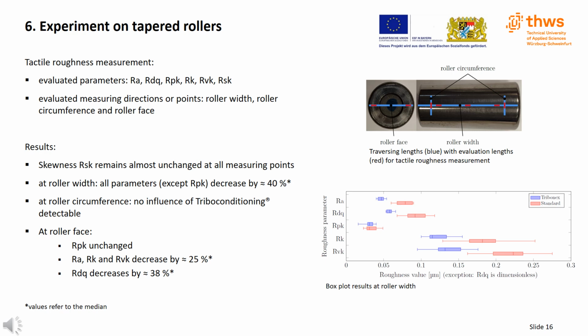At the roller circumference, no influence of triboconditioning can be determined. That is the direction of the grinding process. At the roller face, RPK remains unchanged. RA, RK and RVK decrease by approximately 25%, and R delta Q decreases by approximately 38%.